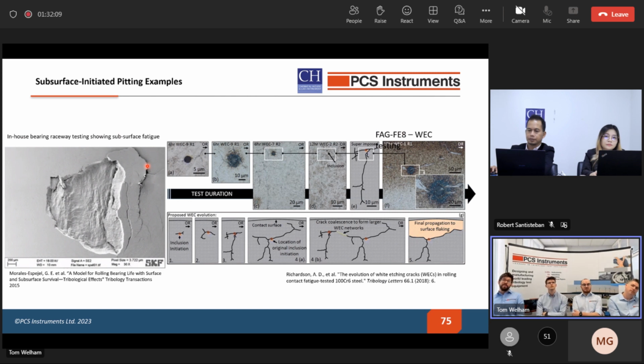There's also subsurface-initiated pitting, so this isn't started by surface defects anymore. We're now starting at defects inside the material. These could be non-metallic inclusions. So if you etch the surface, you can really bring out this inclusion structure. Here they are, and they look very different to the surrounding crystal, and they come up very differently in the etchant. And what can happen is, after lots of over-rolling of the contact from the surface, you get cracks forming below the surface, and they will propagate in both directions. And eventually they'll come back up to the surface and they'll form this pit.